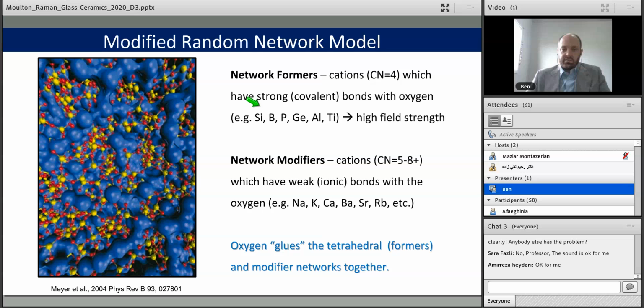The other part of the network, here exemplified by sodium, is described as network modifiers. These break up those rings and create depolymerization ultimately, but they typically have high coordinations, 5 or above, even 8, sometimes up to 10 or 12 if the element is something very large, such as barium or lead, for example. It's important to remember that these are not hard and fast distinctions. There's sort of a gradation related to the field strength of these elements, formers. And in between both of these elements are the oxygen. So when I talk about silicates, what we're really talking about is oxide glasses, and the oxygens are bound to both silica and these modifiers.